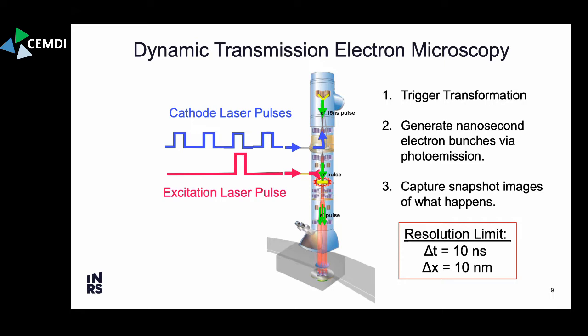It's a very unique electron microscope where you're able to take nanosecond and nanometer time resolution images of irreversible processes, such as a crystallization or phase transformation event. So how an experiment works: we trigger the transformation, and this can be by an excitation laser pulse. Then synchronously, we generate nanosecond electron bunches via a UV laser, which you can actually have arrive in a train. And then we time up the arrival of this train of electron bunches with the excitation of the sample in order to capture a series of snapshot images of this phase transformation.